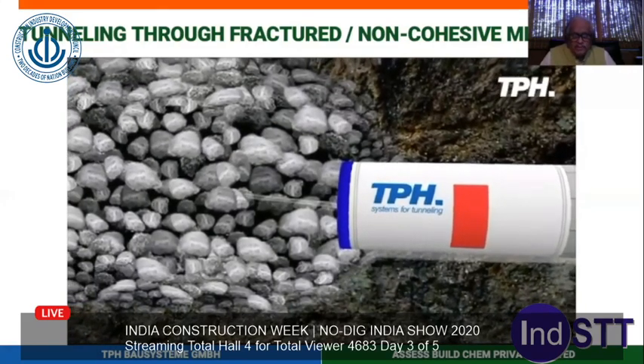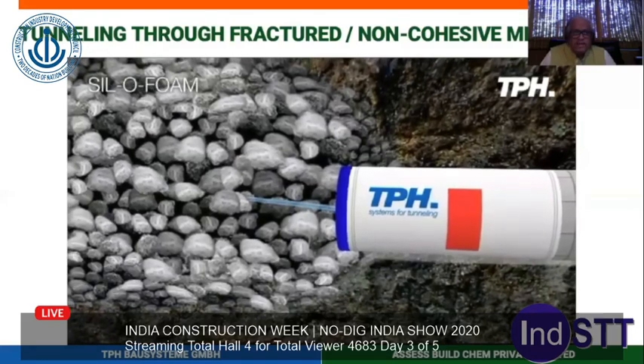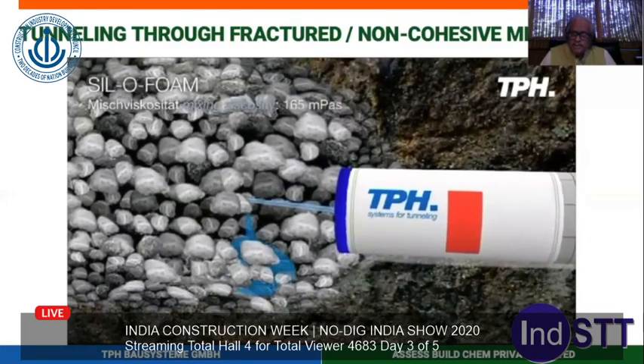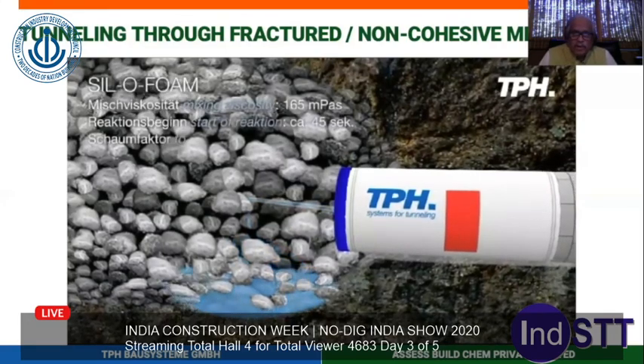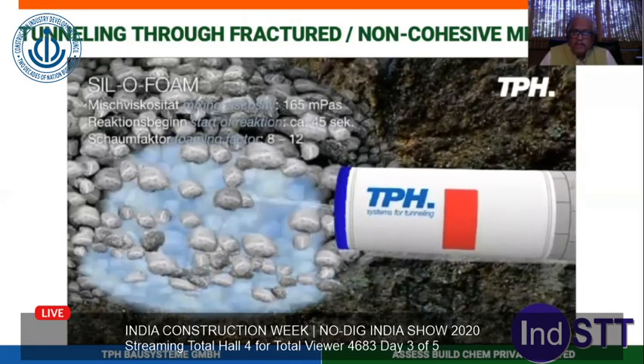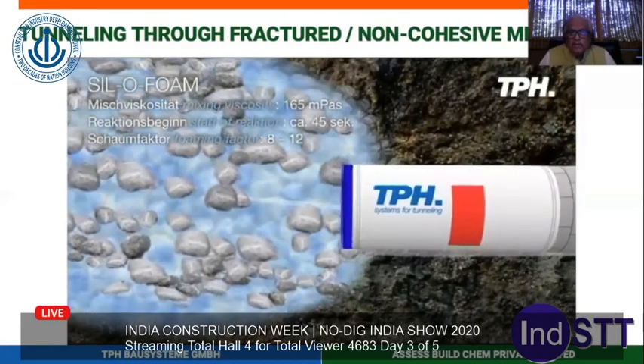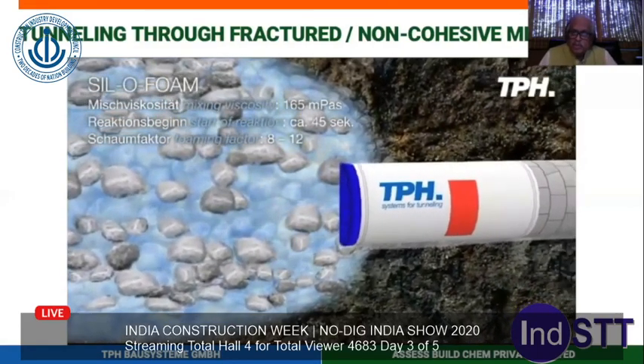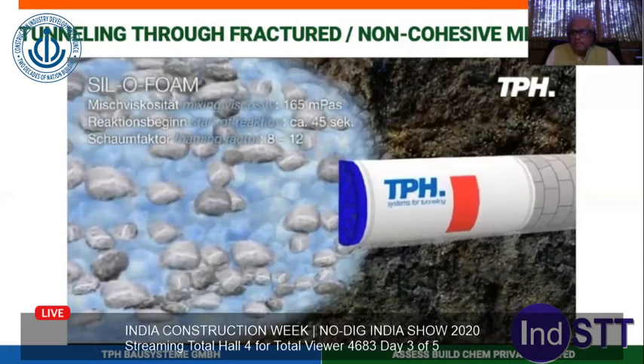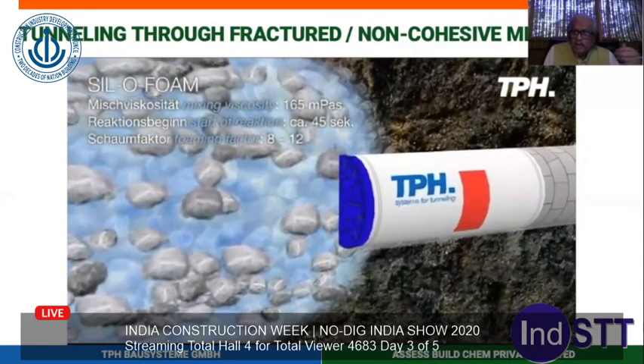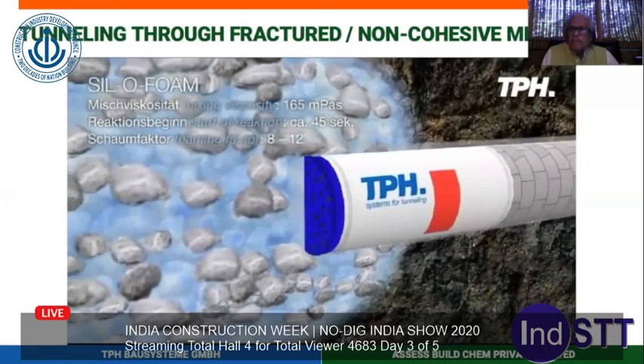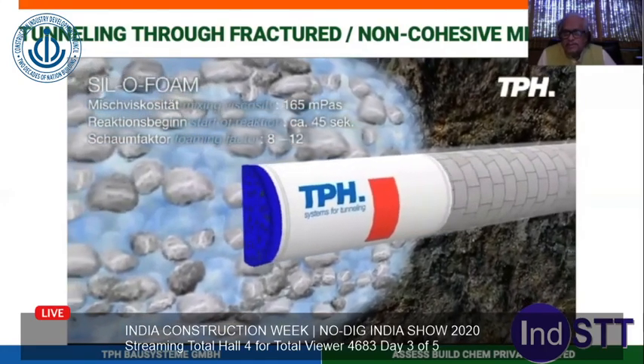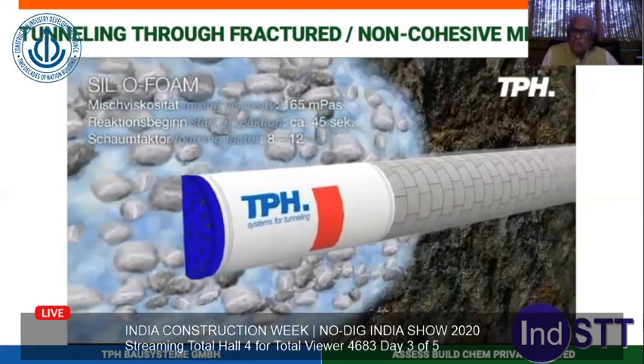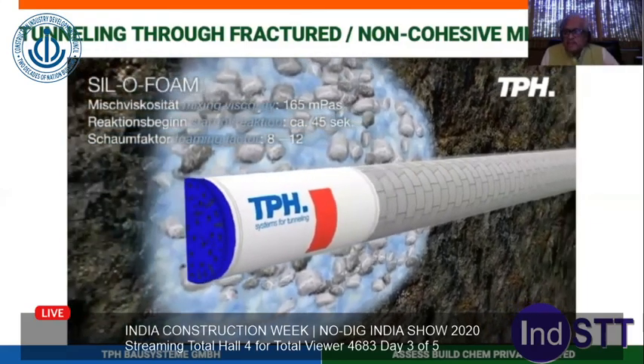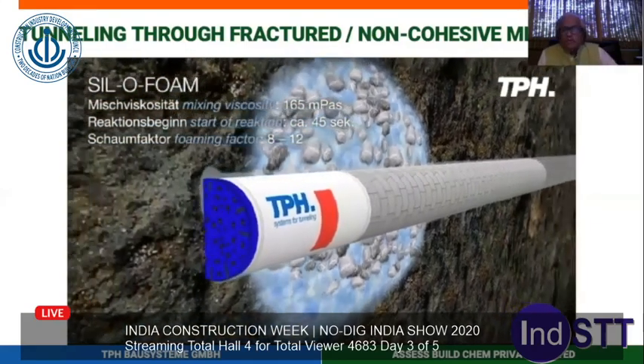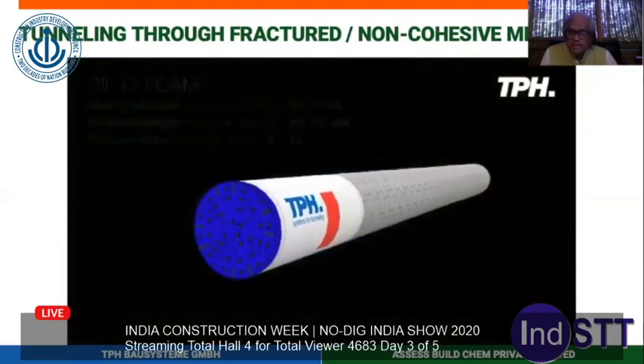So the silicate foam is injected. This foam is not injecting 50 or 60 times. Within 45 seconds, they have maintained the foaming factor to 8 to 12. One thing you have to remember, you'll see some certificates which will tell you my foaming is 1:15 and my compressive strength is 15 Newton. This is not possible, because the tests are done with only 1:1 or 1:3 foaming factors.